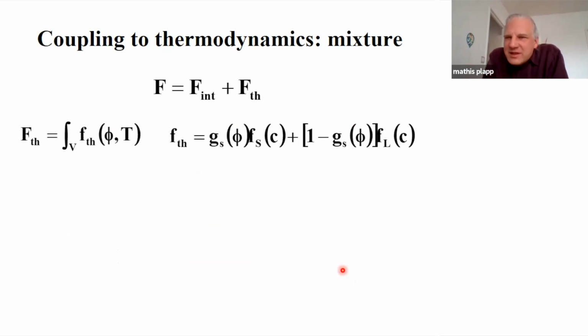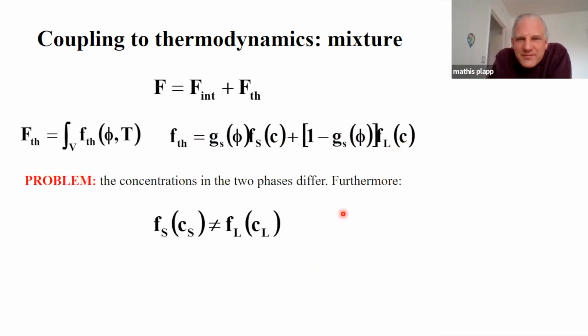But now let's consider the thermodynamic driving force. So if I want to do the same thing as before, that is, I say my thermodynamic part of the free energy is now a superposition of the solid free energy and the liquid free energy with the same weight function as before. I run into trouble. Why? Because this time, well, as you know, in a mixture, if a solid and a liquid coexist, they do not have the same composition. So the composition is different in the solid and in the liquid.